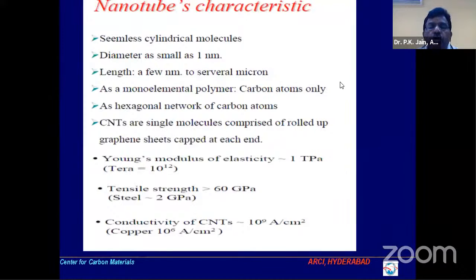Now, as I told you, you people are from aeronautical, so look at all these nanotube features. The Young's modulus is 1 terapascal. The tensile strength is 60 gigapascal. Steel is 2 GPa. Conductivity of CNT is 10 to the power 9 ampere per centimeter square, whereas copper is this. Earlier we looked for copper for high conductivity and steel for high strength. Now this material has a combination of all the best properties, and that's why it is one of the most preferred materials. But of course, challenges are there. We will discuss those challenges also.